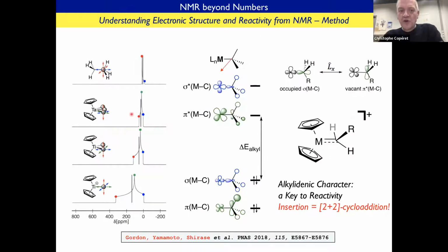Again, to make a long story short, we did all the analysis and we could show that the reason for this anisotropy, as found by NMR spectroscopy, is that delta 1,1 is oriented perpendicular to the metal-carbon bond and is connected to the fact that there must be a very small energy difference between a sigma bond and a pi bond. And you don't expect to have a pi bond between a metal and a basically sp3 carbon, but it tells you that a metal which has a low-lying empty orbital of the right symmetry is able to interact with a p orbital on carbon